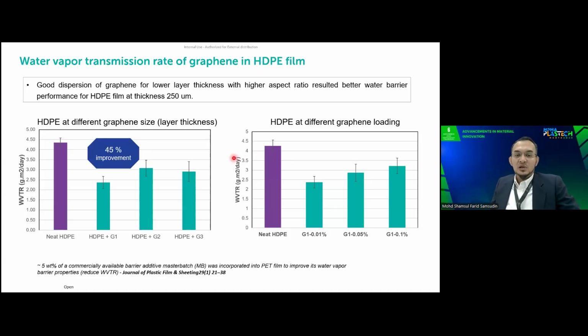And we go into detail on how we study the performance of graphene as a barrier here, with the HDPE film at a thickness of 250 micron. We study different grades of graphene, the finer one and the coarser one. And from here, we notice the improvement for the finer graphene G1 is about 45% as compared to the control HDPE. And from this G1, we further explore the effect of the graphene loading on this WVTR performance. And from here, we notice that when we add more graphene loading, it does not show any improvement in water vapor transmission as compared to 0.01 weight%.